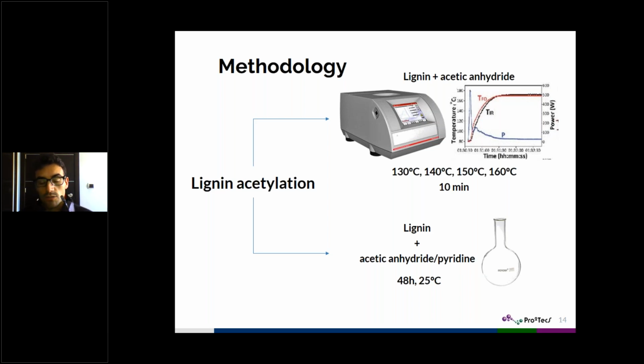And in fact, we can obtain acetylated lignin in much reduced processing time. As you can see here, we only needed 10 minutes to get very good acetylation conditions. To try the different degrees of acetylation, we tried from 130 to 160 degrees acetylation temperature.